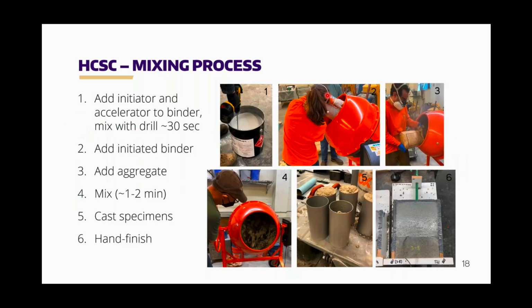One of the reasons that this material is nice is that for the contractor, it's easy. It's pretty straightforward to put this stuff together. You add the initiator and accelerator to the binder. You mix it with a squirrel cage mixer, in this case, for about 30 seconds. You add that and the aggregate to a drum mixer, mix it for a minute or two, and then cast your specimens and finish.